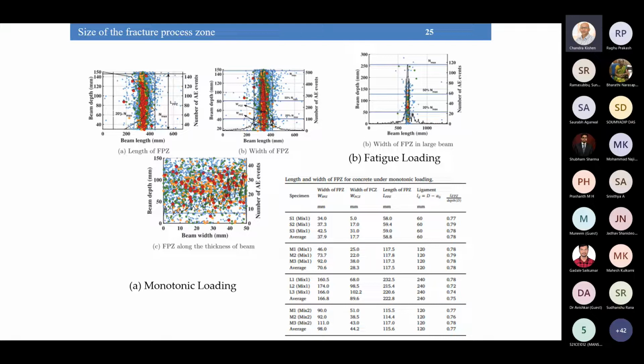And here we can see the thickness. Along the thickness also, what we see is all different energy acoustic emissions are spread across. So that means across the thickness we see all energy events, but due to the free surfaces on these two sides, we see more large energy events occurring in the middle portion. So we could obtain the complete size of the fracture process zone for the case of monotonic loading, which is shown in this table.